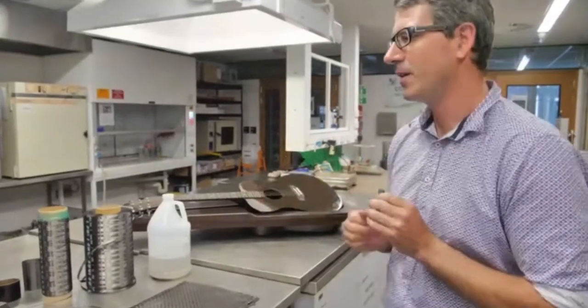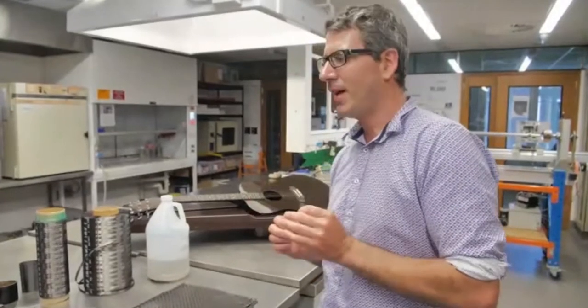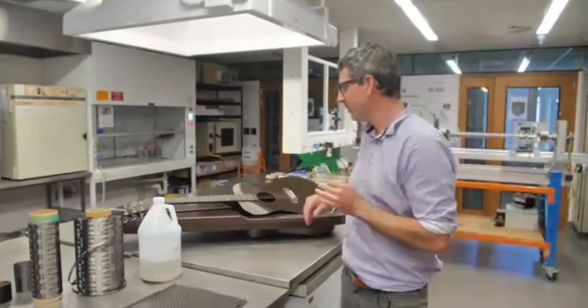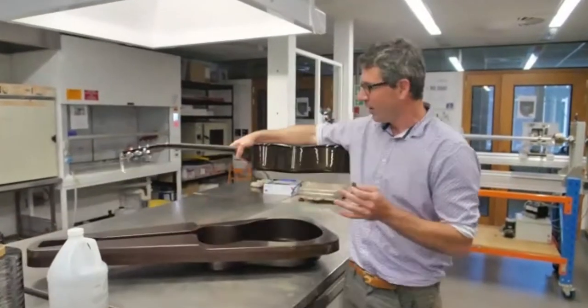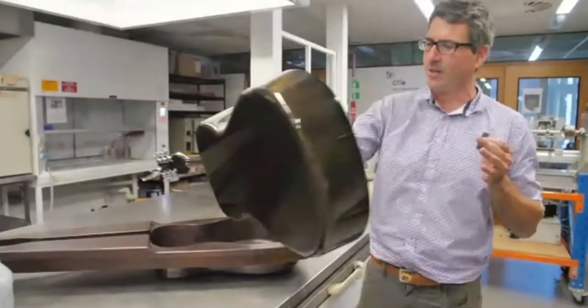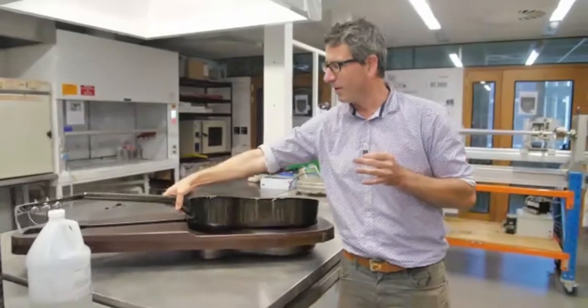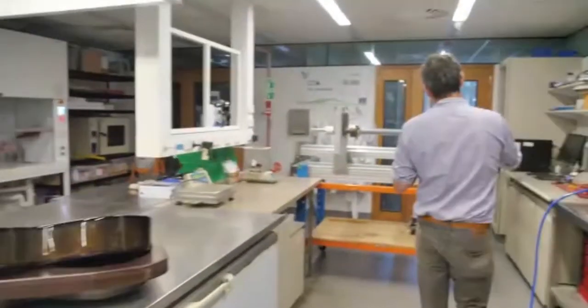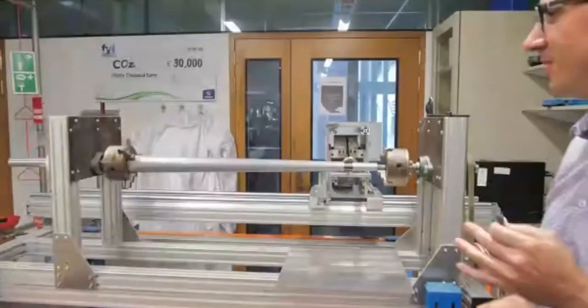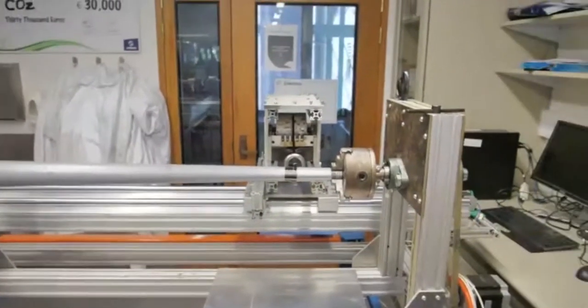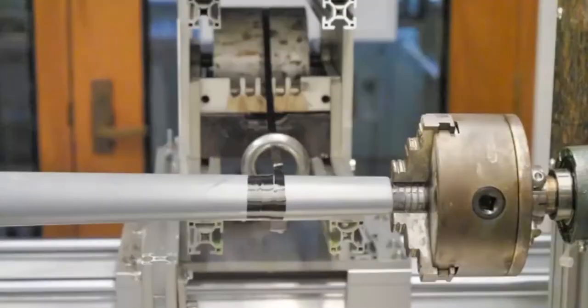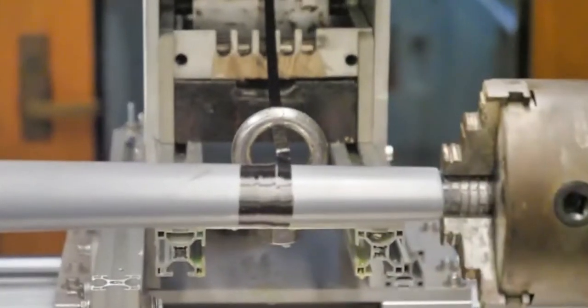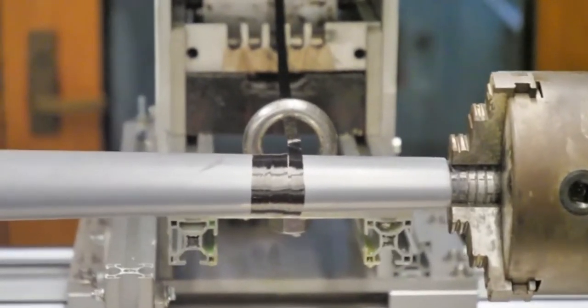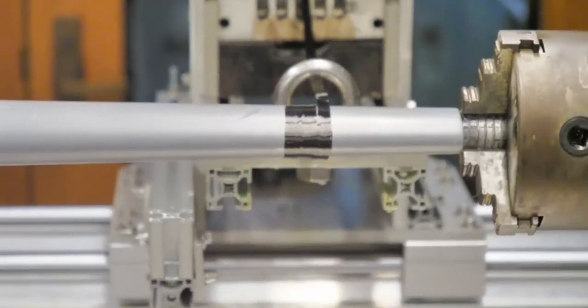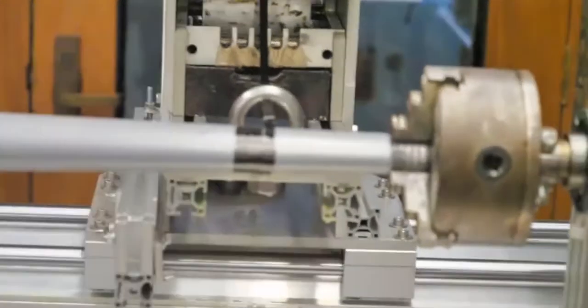And this is really one of the main advantages, that we can basically use similar manufacturing processes that we know from traditional polymer matrix composites. For example, we can do open mold forming, and as you can see, you can make very complex shapes, or we can also do a process called filament winding, and that's particularly useful because many applications such as rocketry or hypersonics have rotation symmetric shapes. With filament winding, we wind a tow of our fiber onto the mandrel, which then gives it its form. And that's really the advantage of the PIP process, that we can use existing polymer matrix composite manufacturing processes to obtain the shape. After that, it's very different.